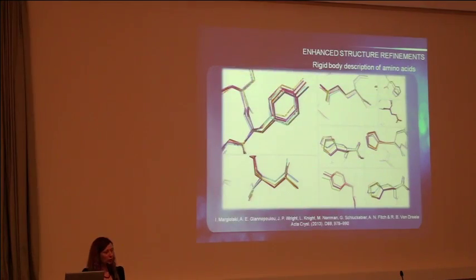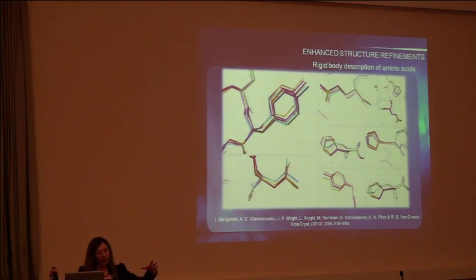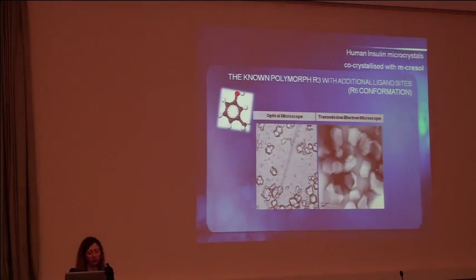Basically, till now, we were refining structures, allowing all atoms to move using, of course, stereochemical restraints, but for us it was very hard because the data are not as good as single crystal data. And with this flexible rigid body, you consider each amino acid as a rigid body, but it can move and it can rotate. So basically, each amino acid is described as a Z-matrix, and this way the number of refined parameters is significantly reduced, and this is our approach these days. The flexible rigid body approach is the way we refine structures.